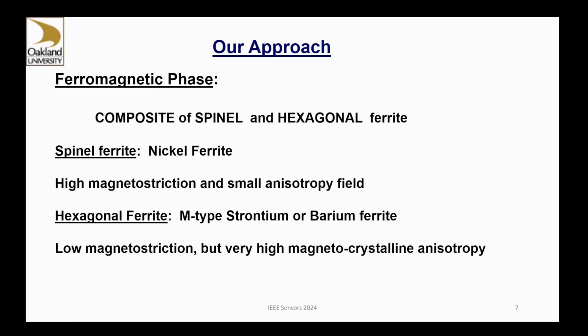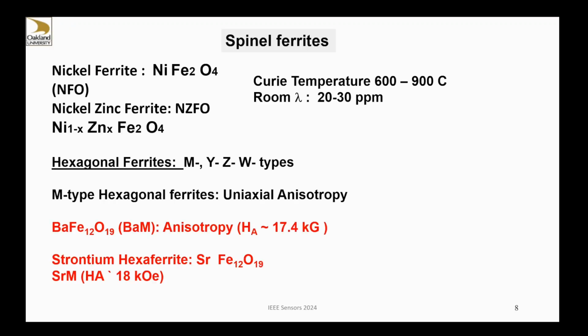So our approach was to make a composite for the ferromagnetic phase with two different oxides. One is the spinel ferrite, which has high magnetostriction. The other is M-type hexagonal ferrite with very high uniaxial magnetocrystalline anisotropy. So we chose nickel ferrite and nickel zinc ferrite for the spinel ferrite, and M-type strontium or barium ferrite for the hexagonal ferrites. We made these two phases separately, nickel ferrite and nickel zinc ferrite, and the M-type ferrites, by traditional ceramic processing. Barium ferrite has very high anisotropy field on the order of 17 kilogauss. Strontium ferrite has about 18 kilogauss.